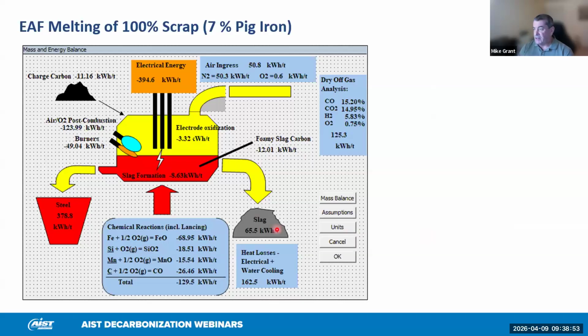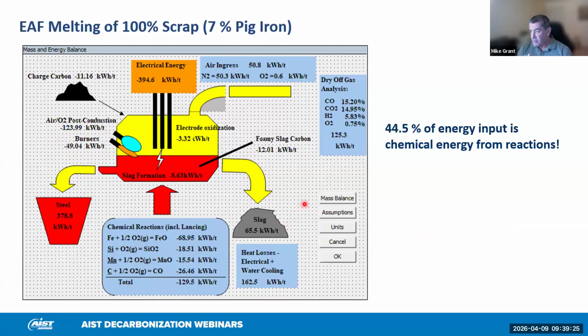All the calculations made were based on this reference of 100% scrap, about 395 kilowatt hours per ton of electrical energy consumption. And you can see in this diagram all of the different energies that are produced from the different reactions with oxygen and carbon. So we have burners, post-combustion, and the bath reactions all contributing to the energy for the whole process. The chemical energy actually makes up about 45% of the entire energy for the process. Electrical energy makes up the other half, but that's the one we always pay the most attention to. So this is the reference.